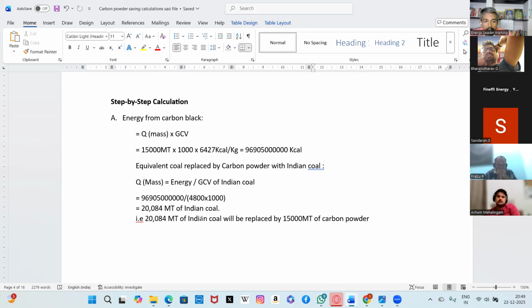The 15,000 metric ton is converted to kg, and the GCV of the carbon powder is 6,427 kilocalories per kg. This much amount of energy is being generated in the fluidization chamber. Taking this as input and dividing by the GCV of Indian coal, we get the amount of coal being substituted by the carbon powder. Take for example, 20,000 metric ton of Indian coal will be used if we replace